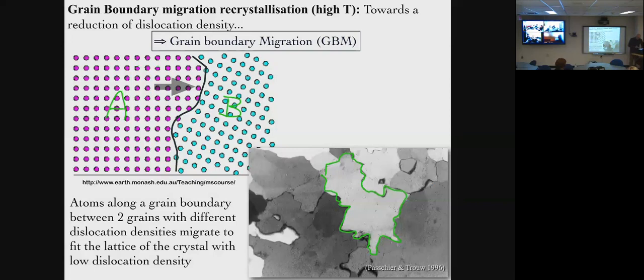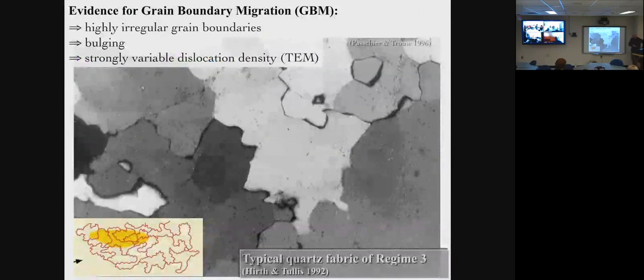So in this case, this grain here would be grain A with a much lower dislocation density than grain B here, and this grain is bulging into that grain and growing at the expense of more disorganized grains nearby. Okay? So this diagram on the left shows really the textural difference between bulging and grain boundary migration. All these grain boundaries in red, right, highly serrated grain boundaries, fairly large grain, typical of a high temperature regime 3 fabric.